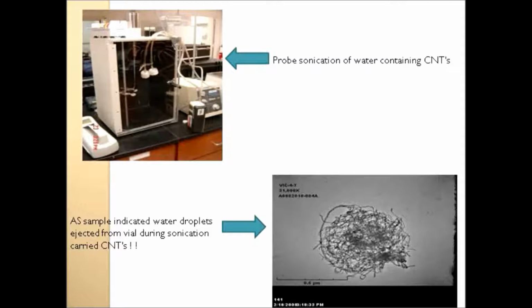The at-source sample showed, here's a really nice example of a TEM micrograph showing the bird's nest. So what we think happened was that it's such a vigorous operation, there's so much energy put into this, that you do get some misting of the water. And those droplets will be ejected from the vial. Within the droplets, that's what's contained in it. And we were able to capture that. So imagine that sonicator working, which it normally would, on an open bench top. Now you're basically dosing your laboratory environment with this material. And they could either remain airborne or they could settle out onto a surface and become a potential for dermal contact.